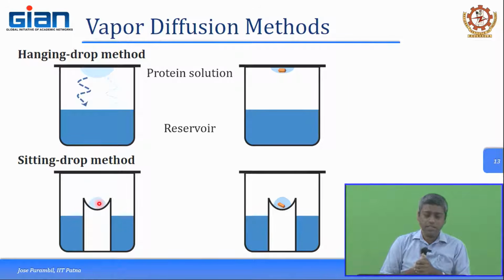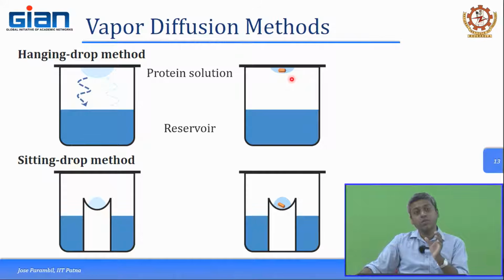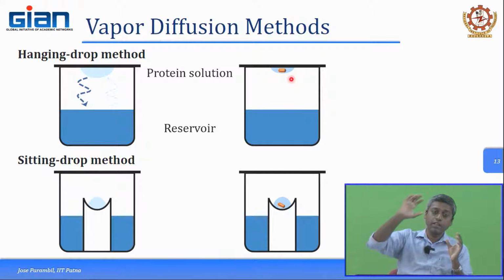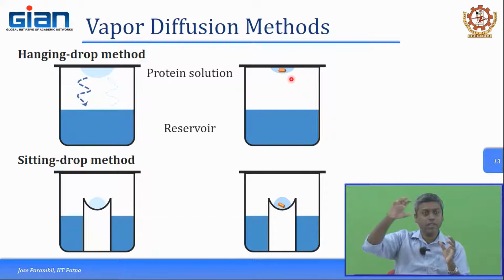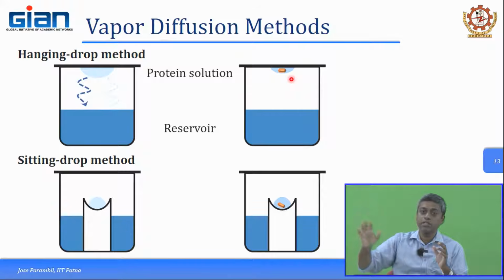Now, why is this important? Because as the name suggests, this is a vapor diffusion method. There is a slow evaporation taking place and slow condensation also taking place. Over time this volume change leads to a very slow change in the concentration. And the slow change is very important because, as we have discussed earlier, in the phase diagrams for crystallization we have the precipitation zone as well as the nucleation zone and the metastable zone. You want the system to go into the metastable zone and into the nucleation zone, but you do not want the system to go beyond that into the precipitation zone. If it goes into the precipitation zone, everything would just precipitate out.